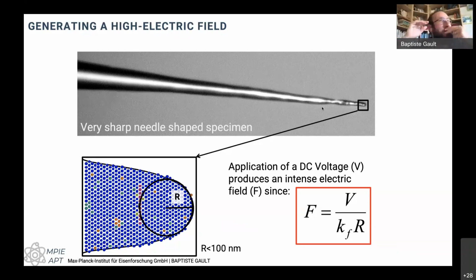I worked on some aluminium plates as a postdoc about 10 years ago, and we wanted to analyze the sample along the 110 direction, and mostly it was along the 111 direction. So I had to cut small matchsticks at a weird angle with the diamond. It's just less practical. With the FIB, it would have taken me maybe half a day to get the results I want. But 10 years ago, access to a FIB was not simple. It's definitely not as simple as it might be today.